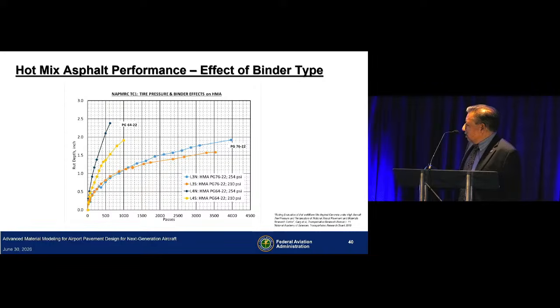And this chart here shows the effect of binder. So this is unmodified binder and polymer modified binder. And again, very significant difference in the performance.